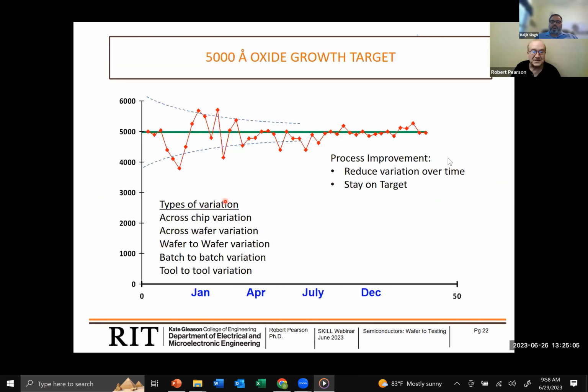And here's an example over time of an oxide growth that's targeting 5,000 angstroms. And you can see that it's kind of all over the board, but maybe we're making some changes and improvements and we've tightened it up and we're on our average and our deviation is much lower than it was months ago. So types of variation that we're talking about are variation within one chip, which could cause problems, variation across the whole 6-inch wafer, from one wafer in a batch to another, from one batch from one day to another day, from one tool of the same type to another tool. Chasing down and reducing variation is the process engineer's daily challenge.